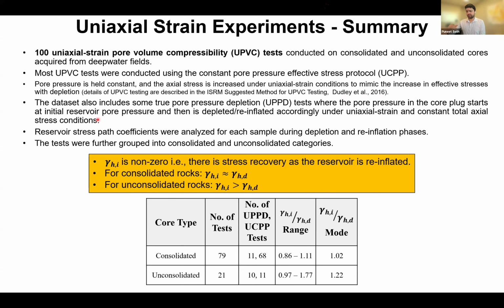So as I said, 100 tests on both consolidated and unconsolidated. Most were done on consolidated, 79 on consolidated samples, 21 on unconsolidated. We measured many things like compressibility, but also looked at the reservoir stress path during both depletion and reinjection. And what we see from the summary of the results is that the injection coefficient is non-zero. So that's number one. And there is actually stress recovery when you're injecting or the reservoir is being reinflated, right?